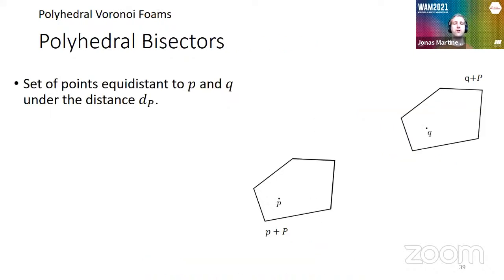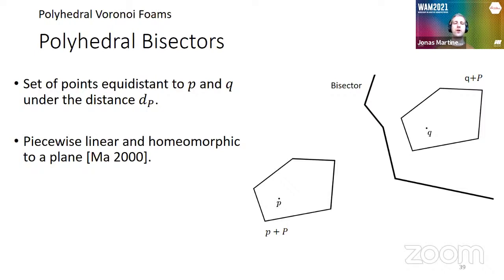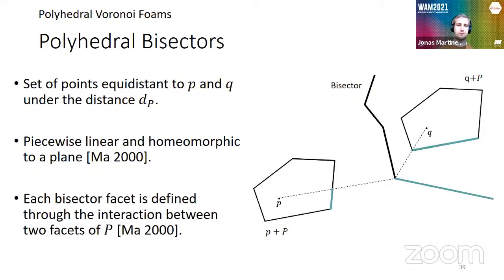Now we focus our interest on what happens with the set of points that are equidistant between 2 points under some distance. For the Euclidean metric, you put a line between P and Q and you get the perpendicular bisector in the middle. This is very easy. But with this kind of distances, you get more strange bisectors. But we know from theory that they are composed of linear patches. And more importantly, they are homeomorphic to a plane. This means that we don't have isolated pieces of the bisector. And that's the key property that we exploit, that each bisector face is actually defined by the interaction of 2 facets. I'm going to go into details of that.